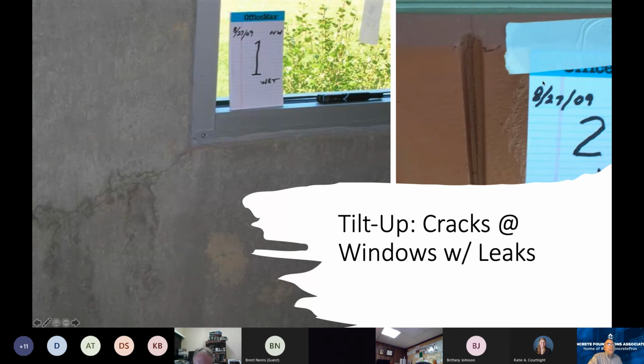And in this particular case, where the vertical reveal is, what we found is that neither one of these was reinforced sufficiently. So the structural design of the panel was based on the full thickness to the left and to the right of this vertical reveal, and the vertical reveal reduces the structural thickness, and so they ended up with less than the amount of coverage that they designed over the steel reinforcement, and that was a weakened plane, and so cracking occurred there. Now, it's not a structural crack, but it's a crack that occurred that they couldn't control. And so it was a crack where moisture, it was bad enough, it went full thickness, and moisture was allowed to get in underneath the windowsill right here at the top of the crack that they couldn't seal off.